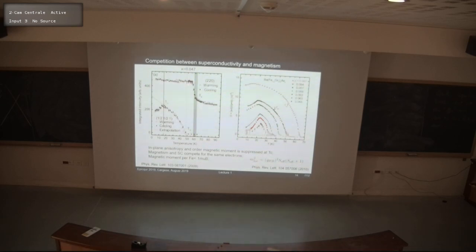And here are graphs showing now the magnetic response of the system from neutron diffraction on a similar composition of the same family. This is now the neutron diffraction signal, integrated intensity versus temperature. And in this graph, it's really clear that we have these 2 disentangled transitions.